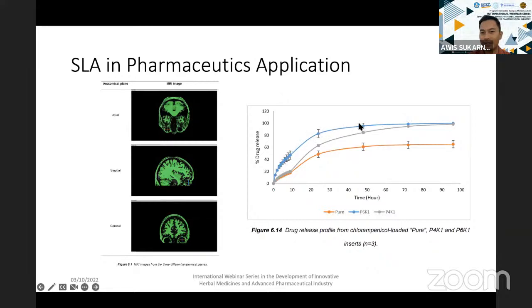It means at this point they have already released most of the drug. But here you can see the release profile wasn't as smooth as with PEG 6000. For PEG 6000, you can see a quite nice curve until around 24 hours, when most of the drug has been released and it starts to plateau. But here it releases slowly, and then suddenly it jumps quite fast.